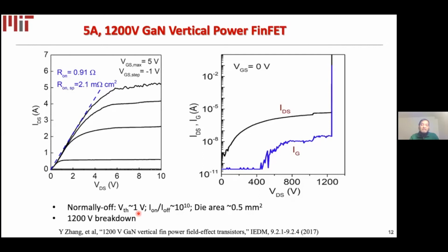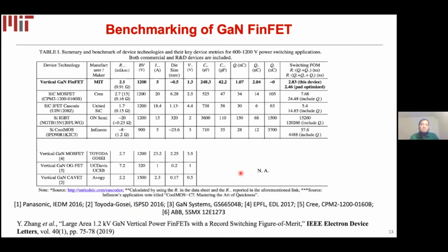And not only that, if we also look at the switching performance of the devices, these devices show competitive performance among all the silicon carbide and silicon power devices in terms of both current density, chip area, and the switching charge and switching speed. So that was a very promising start, and all of these demonstrated devices were made on a native gallium nitride substrate or freestanding bulk gallium nitride substrate.